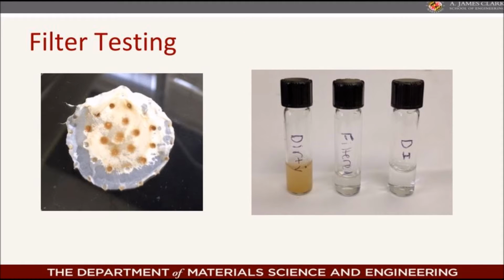In our most recent work, we have begun to characterize the filtration properties of our membranes. We used optical measurements to determine the turbidity of dirty water before and after filtration. The dirty water was approximately 1,300 times more turbid than deionized water, while the filtered sample was merely twice as turbid. This initial test appears quite promising, but further quantitative testing is required.